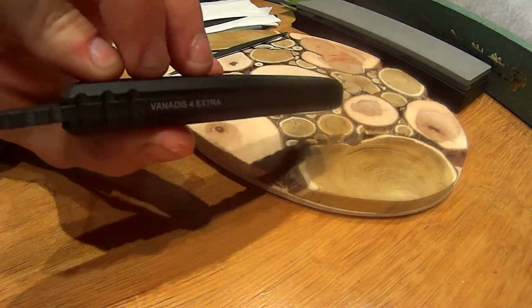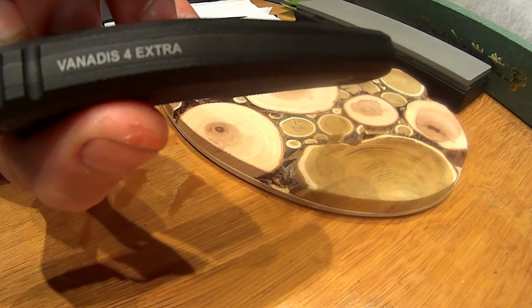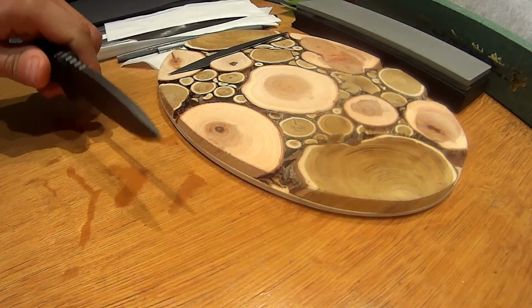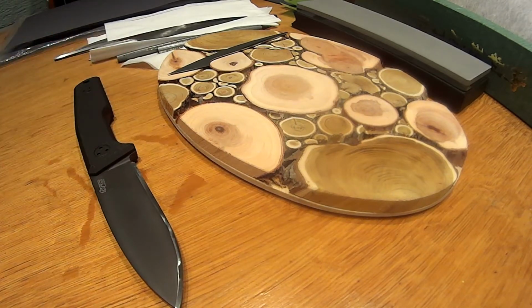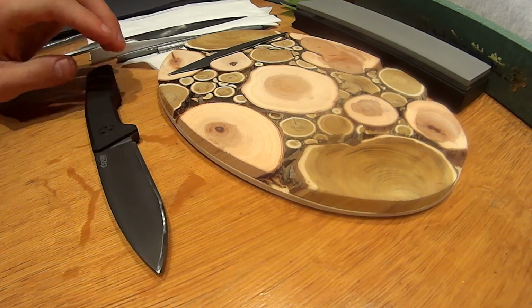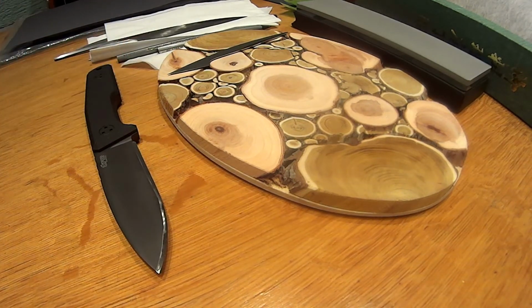This knife is made out of Vanadis 4 Extra and has been tested extensively for edge retention. It performed very well. It has cut longer than some other knives made out of more heavily, higher carbide steels. That's surprising. And it also demonstrated reasonable edge stability relative to its high wear resistance. So we can consider this heat treatment to be not far from optimal. It is definitely decent.